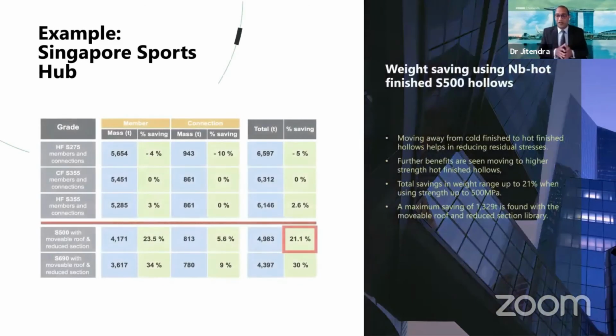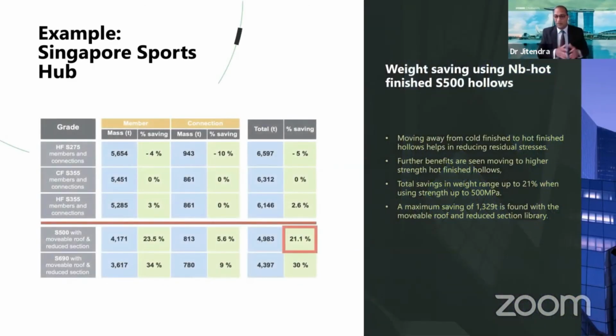So overall, by going from a hot form 355 to a cold form section, to a 355 to a hot form 500 hollow section, we were able to save about 21% if that project had gone ahead and done this, and a maximum saving of about 1,300 tons of steel, so significant savings in tonnage.